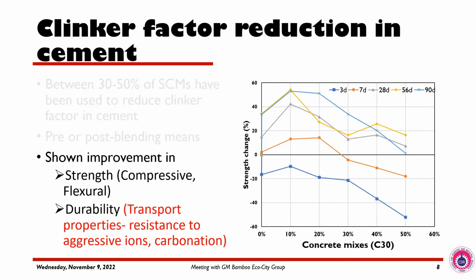I did this work I think last year, where I replaced cement with between 10 and 50% of calcined clays. And I cured it at 3 days to 90 days to look at the performance. Now, what I did was to look at the common concrete grades we use in Ghana. When you go to many sites, it's between C25 and C30. So I used C30 to design my concrete, and I normalized this to C30. So the zero that you see here is a normalized concrete of C30.